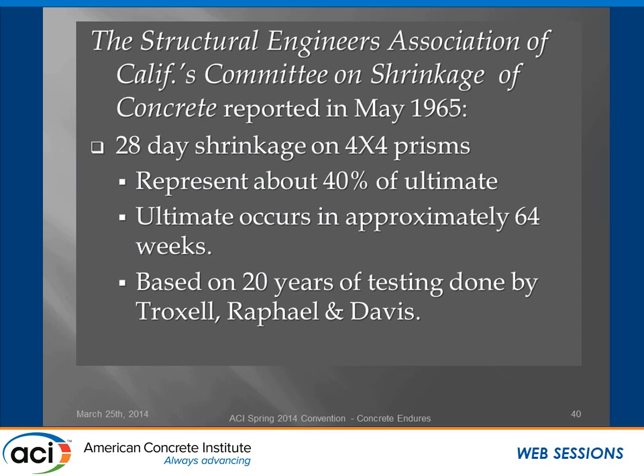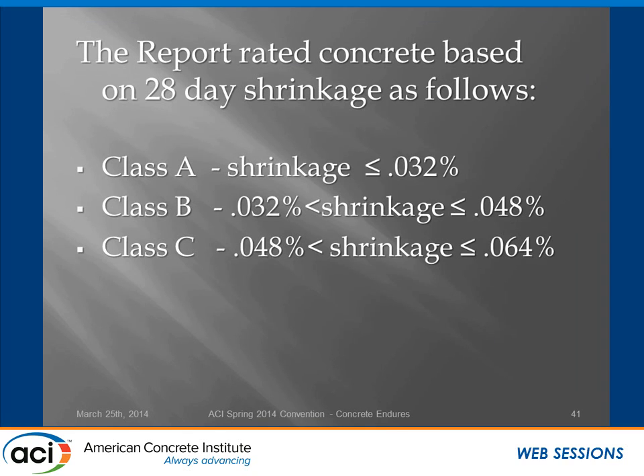In 1965, the Structural Engineers Association's Committee on Shrinkage did some work, and they reported the following. First, the 28-day shrinkage that we're fond of specifying, 4x4 prisms, represents about 40% of the ultimate shrinkage of the concrete. And the ultimate shrinkage occurs after 64 weeks or so. Based on 20 years of testing by Troxell, Raphael, and Davis,